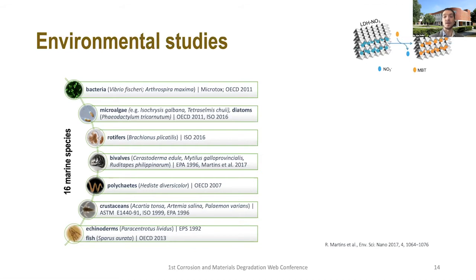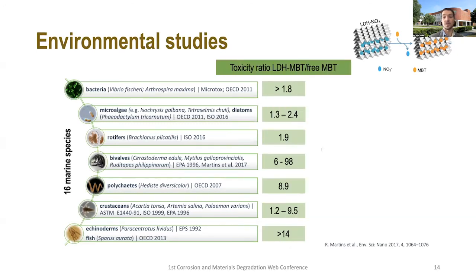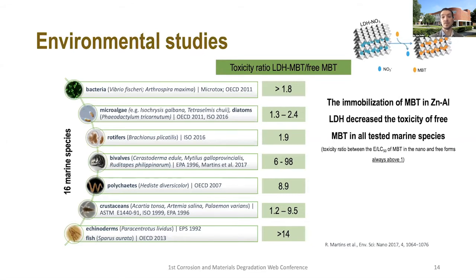So in this study with colleagues from the biology department, we exposed different marine species to the MBT in the free form and intercalated in LDH. And we could see that in all the cases, the toxicity of the MBT decreased when it was immobilized. And it's consistent with the fact that not all MBT is available at once to work on the surface, and in consequence not available to the environment. So this was a positive effect. The LDH itself with nitrate did not have significant toxicity, no or low toxicity at all. And we could see that when intercalated, the corrosion inhibitor was decreasing the toxicity of the free compound.